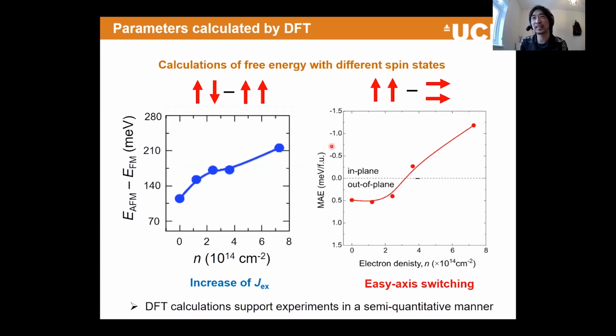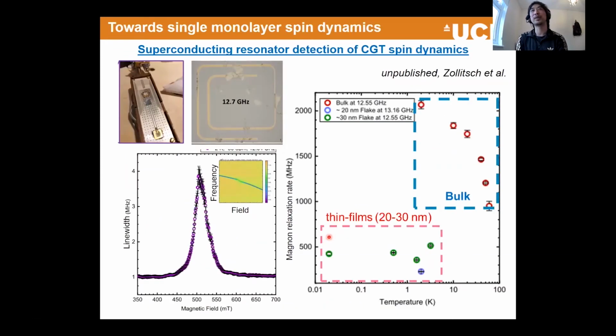So I just want to say that this is also supported by the DFT calculation. And finally, I just want to spend 1 minute to explain. I just switched to a completely different topic, but within one slide. So using not only the electric field, we try to measure real spin dynamics in the monolayer regime. Still, this is work in progress, and thanks to a superconductor resonator, a very sensitive resonator made by John Morton's group and colleagues through this quantum technology initiative, we make this resonator and put the 2D material on top of it.